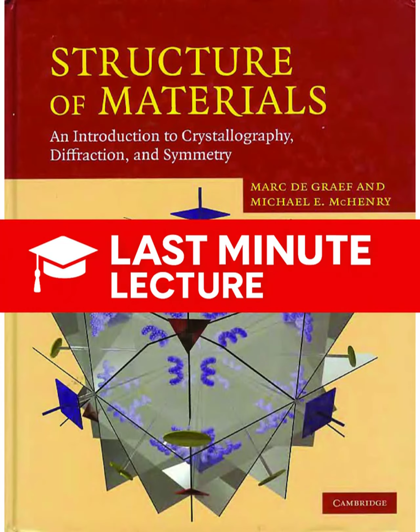So the curve for gold would drop off very steeply. Much more steeply than the curve for a light element like carbon, where Z is only 6. Its electron cloud is tightly compact around the nucleus. This reveals that the spatial distribution of electrons is fundamentally encoded in the angular dependence of F.